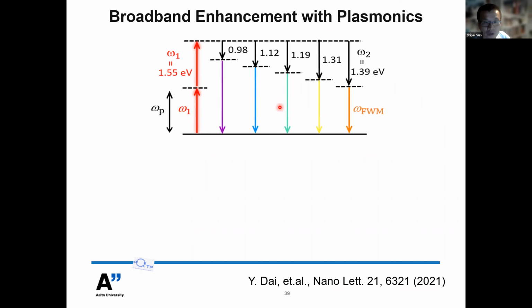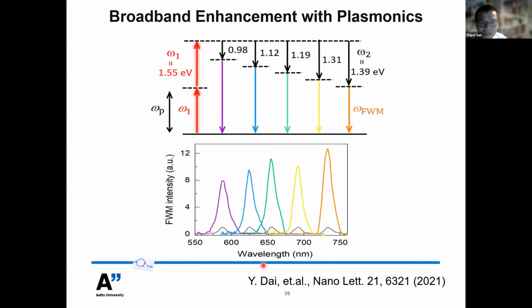What we did here is we fixed the pump frequency, and then we changed the idler frequency to generate the tunable 4-wave mixing signal. You can see here, because we fixed the pump wavelength, which is always on resonance with the plasmonic resonance of the nano antenna, that means the 4-wave mixing signal will always be enhanced. You can see this is our broadband enhancement measurement result. Without the plasmonic resonance, the 4-wave mixing signal is very weak.